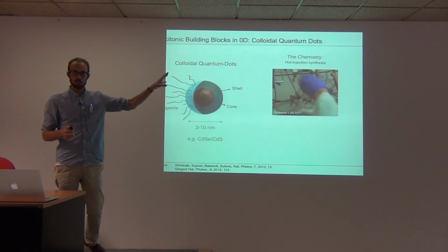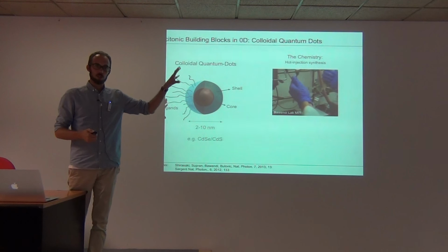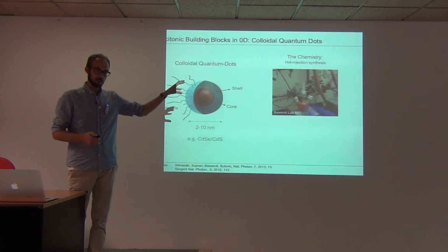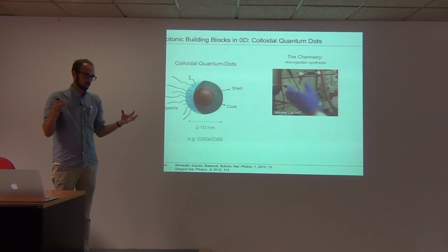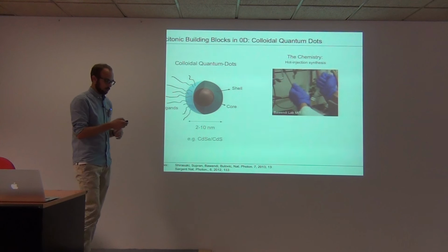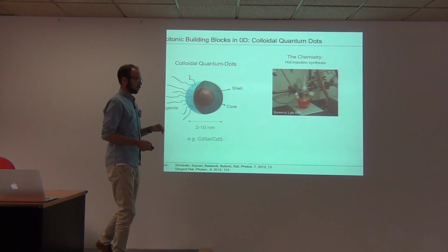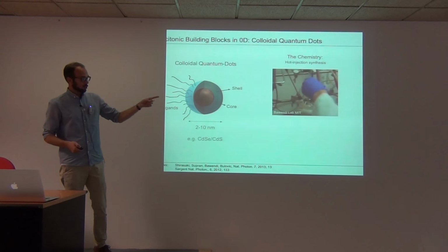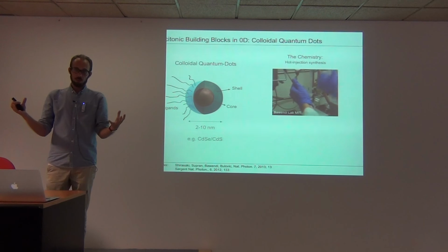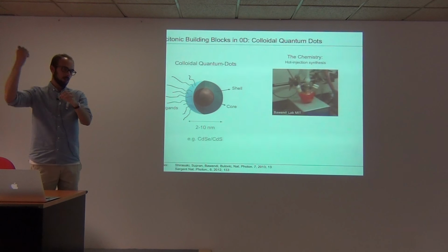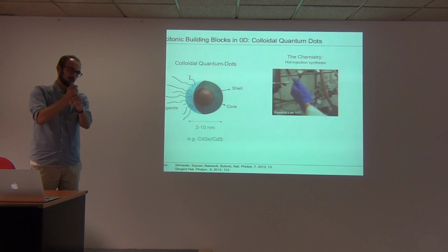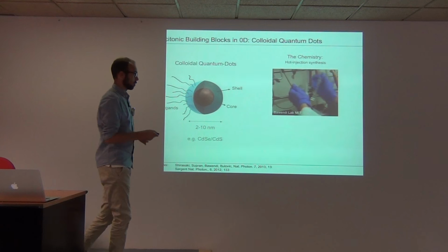This comes back to this size polydispersity. You need to create all the nuclei instantaneously, such that all of them start growing at the same time. So you can imagine, this is a relatively small scale synthesis. In the commercialized systems, they're talking about 5 or like kilogram scale synthesis. So then it's basically an automated gun that is injecting the precursors in that solution.